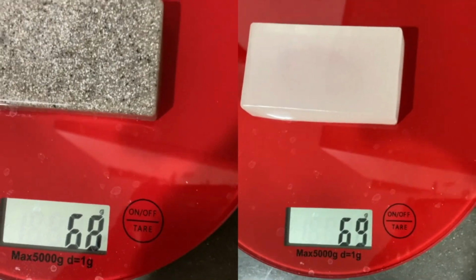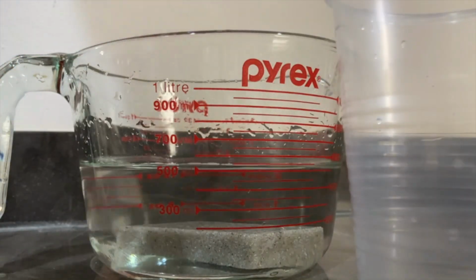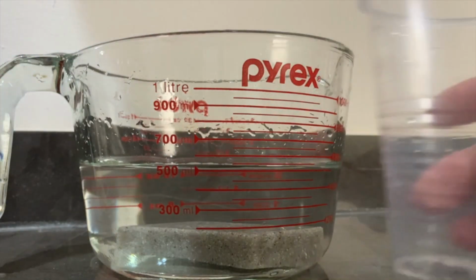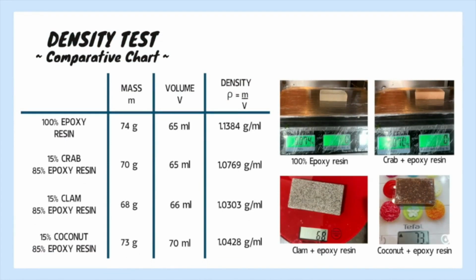Then, the test tube was placed in a container with 500 milliliters of water. After it, the differential volume was measured with a syringe. And finally, density was calculated with mass and volume. The most dense material was the pure epoxy resin. The composites had a lower mass-volume ratio, being the clam composite the lightest of